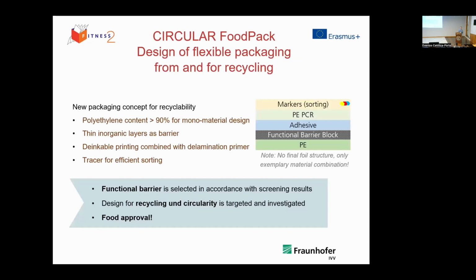And in the end, we want to give a guideline for a design of a flexible packaging which comes from recycling, so with a recycled content, and is able to be recycled again. So there we focus on a monomaterial design with a very high content of polyethylene and a thin inorganic layer as a barrier. And it may also have a de-inkable printing combined with a delamination primer on it, and maybe also a tracer for the efficient sorting of food packaging materials. And in the course of the project, the functional barrier will be selected in accordance with our screening results, and the design for recycling and circularity will also be targeted and investigated to have, in the end, a target of food approval of the technology.